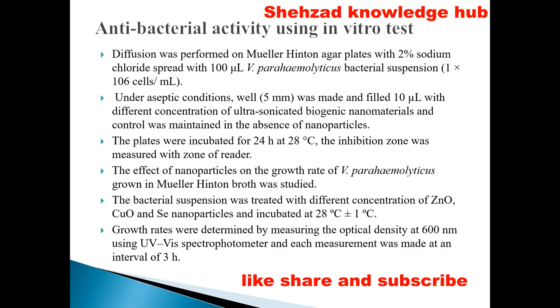The effect of nanoparticles on the growth rate of Vibrio parahaemolyticus grown in Mueller-Hinton broth was studied. The bacterial suspension was treated with different concentrations of zinc oxide, copper oxide and selenium nanoparticles and incubated at 28 plus or minus 1 degree centigrade. The growth rates were determined by measuring the optical density at 600 nanometers using an ultraviolet spectrophotometer, and each measurement was made at an interval of 3 hours.